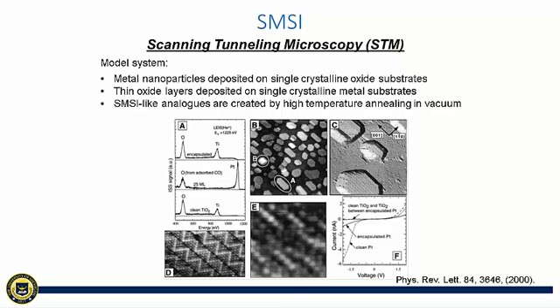For example, a number of elegant scanning tunneling microscopy studies have been performed on model catalysts consisting of metal nanoparticles deposited onto single crystal oxide substrates and vice versa that confirm this behavior upon heating in vacuum and also provide structural information about SMSI-like analogs. Shown here are some representative results which demonstrate that migration has occurred. This is shown in panel A by low-energy ion scattering. Also, how the model catalyst looks at various magnifications, shown in panels B through E, and finally an IV curve that provides some information about the electronic transport across the oxide layer.